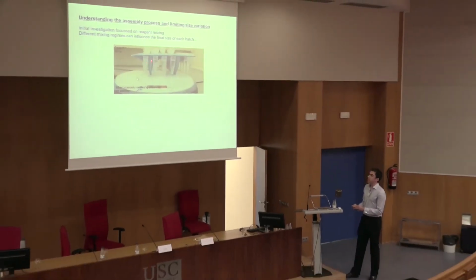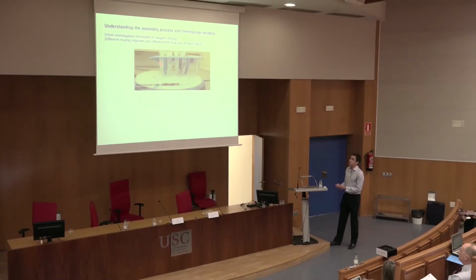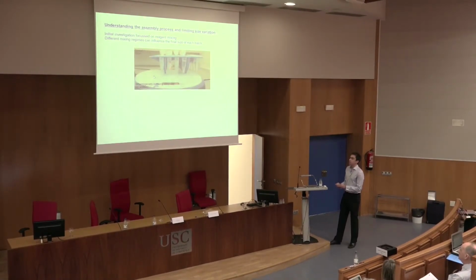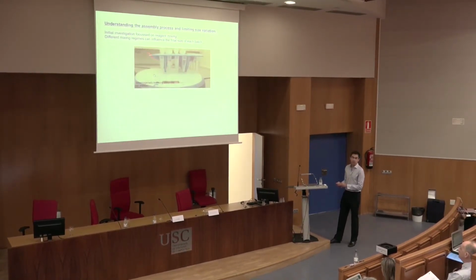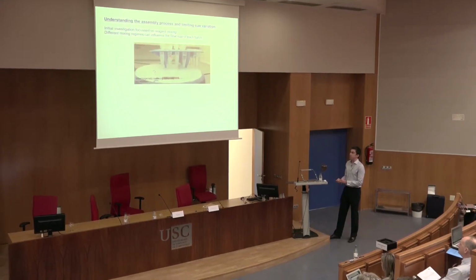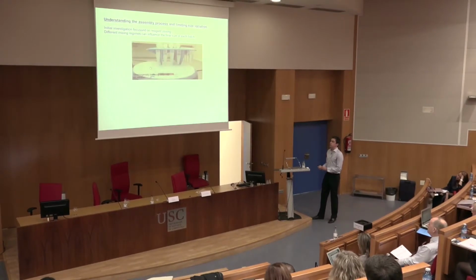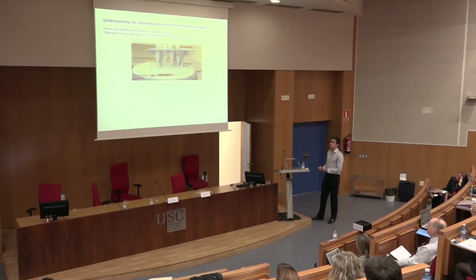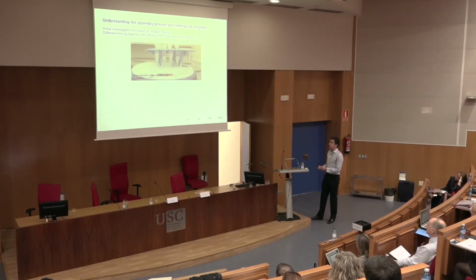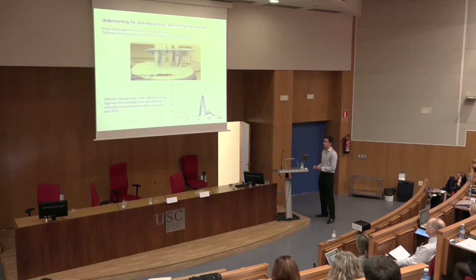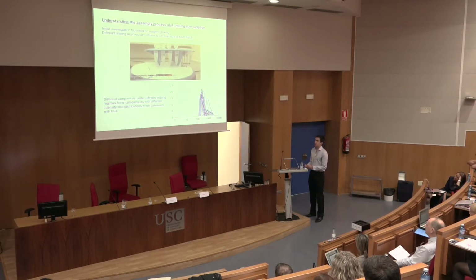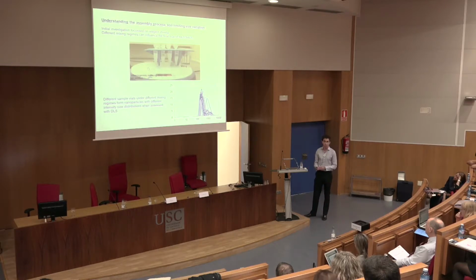Similarly, if you look at this second tube and the 4th tube, mixing actually only happens within this 3/4 length of the tube. It doesn't happen in the top part. So your effective concentrations are different between the tubes. I'm showing this basically to highlight that mixing is very important, and it can lead to a distribution of sizes in your DLS data at the end, which is what we saw when we prepared our materials in this way.